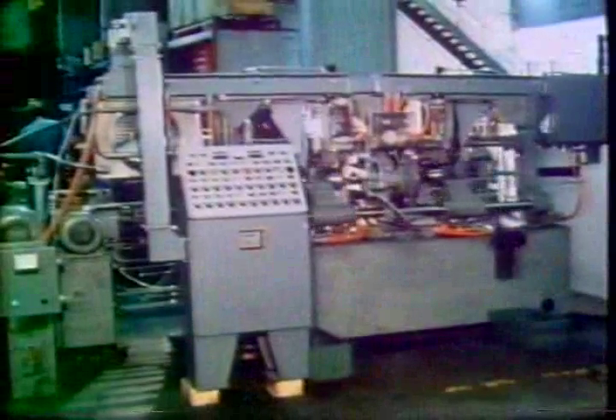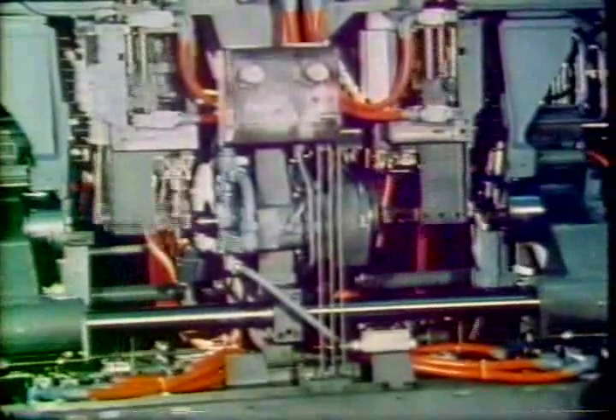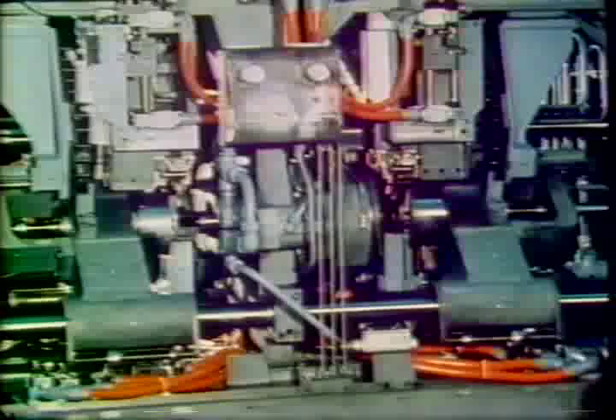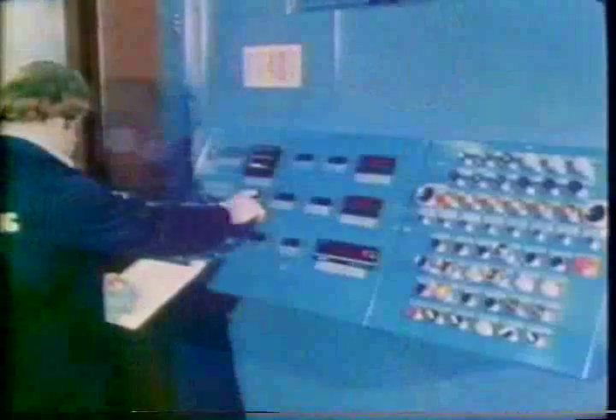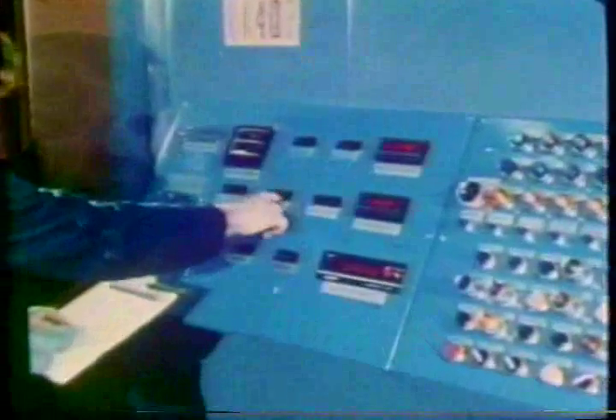In addition to high production rates and superior bonding, inertia welding has many other advantages over conventional welding processes. They include lower energy requirements, no need for filler materials, flux, or other consumables such as shielding gases, consistent quality, and forged weld joints. Because it is an automatic machine-controlled cycle, inertia welding also offers freedom from operator control. And because upset is so consistent, length lost being typically 15% of the workpiece diameter, upset can be used to check product quality. For quality control purposes, electronic machine monitors check and compare the set parameters against the actual performance of the machine.